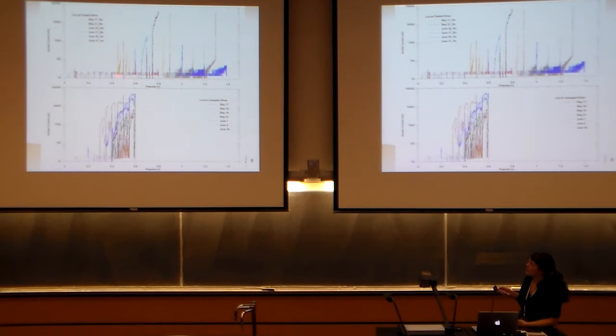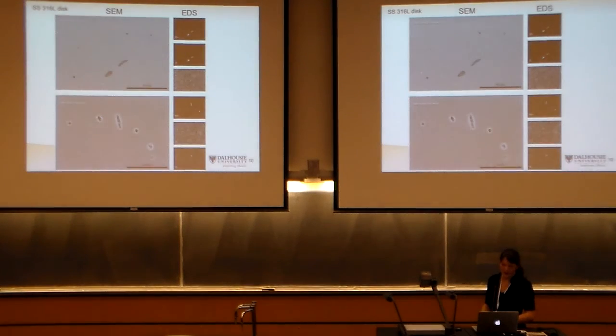So you see, on average, they usually don't start pitting until between 450 and 700 millivolts, while some didn't even start until 1 volt or higher, as you can see with this dark blue or the gray sample. While the untreated samples all started between 300 and 400 millivolts, and by 600, the surfaces have been completely destroyed, and there's no point collecting further data.